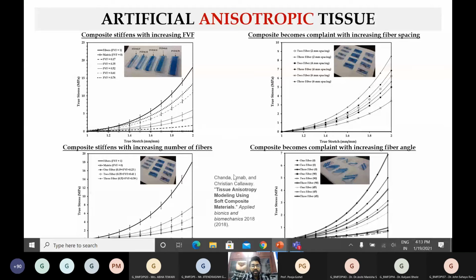So what did we observe? When we increase the amount of fibers or the fiber volume fraction, very intuitively the material property goes up. The true stress versus true stretch goes all the way up. It is getting more and more stiff. As the fiber amount goes down, it is much more compliant. The composite becomes compliant with increasing fiber spacing. When we have more spacing between fibers, which is also fairly intuitive, the composite or the soft artificial material gets more and more compliant, meaning it's not very stiff.